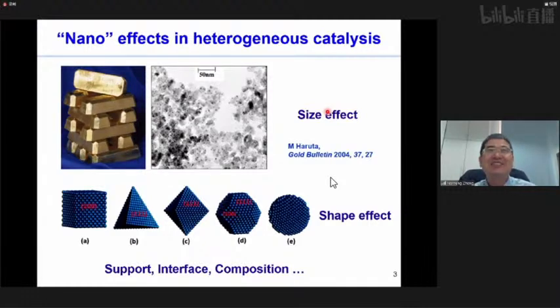In the literature we have already observed so many nano effects for heterogeneous catalysis, such as size effect. A really typical example is gold catalyst. We all know that gold is catalytically inactive in bulk form. But if we deposit gold nanoparticles on a high surface area support, like an oxide, for example iron oxide, we can make a highly active catalyst, even for CO oxidation at very low temperature. And we also have many other effects like shape, support, you name it.